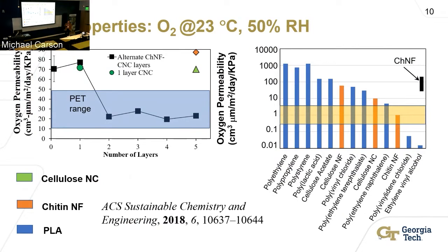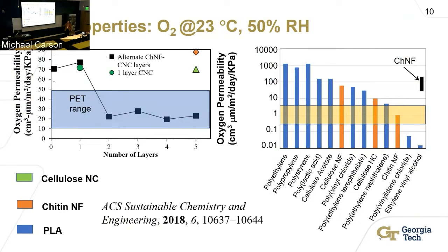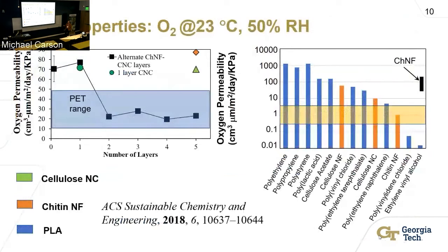These were chitin nanofibers spray-coated onto the substrate. This was a spray process — it dries very quickly, in a few minutes — so it's very manufacturable. But because they're drying so fast, they don't have time to align and pack really tightly. We're relying on the electrostatic attraction at the interface to create a dense interface that slows down diffusion. We were in the right range, but we wanted to go lower.